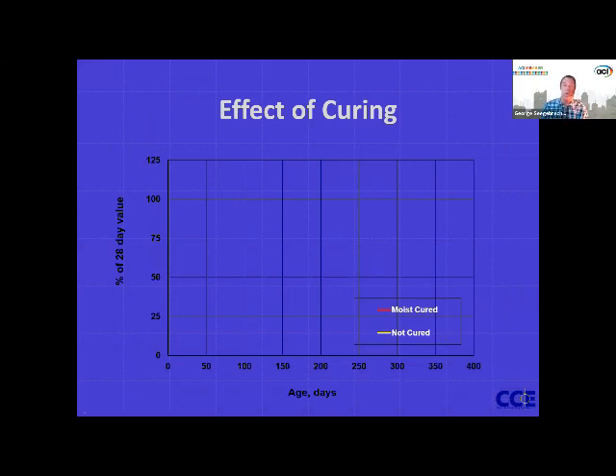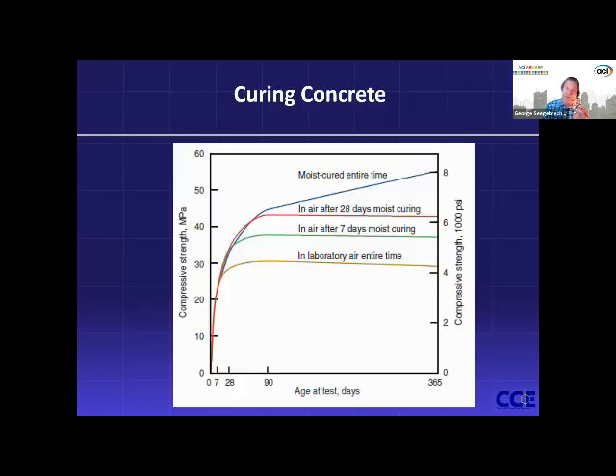Okay, so we all know curing is good. This is a kind of a slide that shows, okay, here, if we're going by percent of 28-day strength, the 100% would be your 28-day strength right here. Boom, we cure and we get this kind of performance. You don't cure and you fall significantly short. This is the same graph next. I just like that it adds the days themselves, showing the incremental relative change from curing and not curing. It does make a difference.